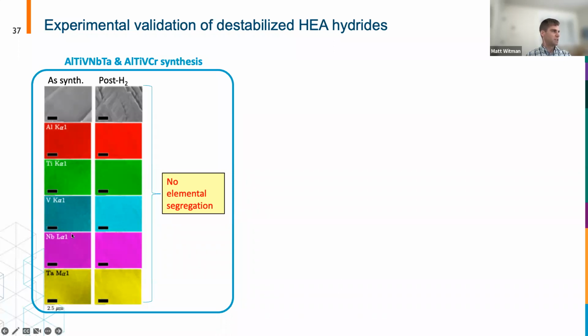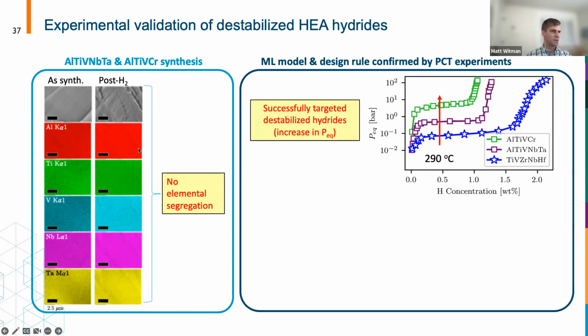You can see here some nice EDS images of before and after hydriding for these samples. You don't see any elemental segregation. They remain high-entropy alloys as you cycle them. And then if we go and do the PCT curves, again, blue is the original material, and in squares are these new aluminum containing compounds that we predicted, and you see several orders of magnitude increase in the plateau pressure.